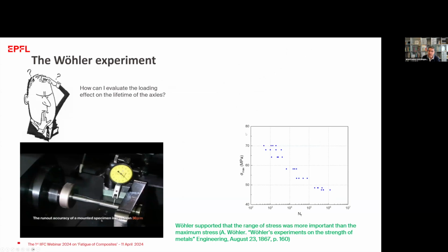So imagine that this is my graph. I'm doing a test when the maximum stress that I'm applying is 70 megapascal. I count the number of cycles to failure. It is, in this case, it might be 7,000 cycles. I put this point here, and this is the first point that I have. If I repeat the test at the same stress level, I have the repetition of points that show also the scatter of the fatigue data.